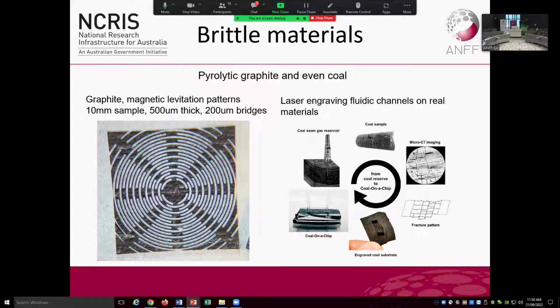Now, this is not something that you'd want to do mechanically, and that's to work with graphites and coal and things like this. To give you an idea of scale, the part on the left, that's about 1 centimetre, so that's 10 millimetres in size. A lot of the channels and bridges that we're leaving behind after laser machining are only 100 or 200 microns in width. That's very, very fragile when you're doing that out of pyrolytic graphite, but we can get away with it. So I guess that's one of the other key messages with laser machining: while there are some forces involved, it's much closer to a non-contact process than machining and things like that. And you certainly don't want to be taking your dirty coal samples into the clean room to do lithography on them.